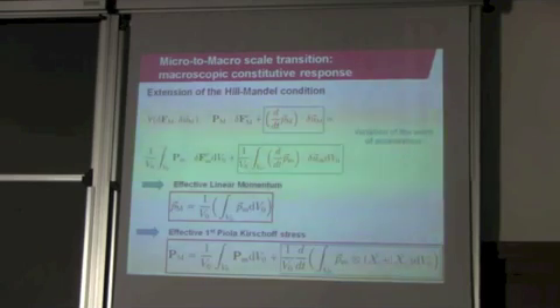And the effective Piola stress, so Francesco, it's Piola stress. By the way, just a side remark, it turns out that in homogenization at large strains, the Piola stress is a much handier measure than the Cauchy stress. So all homogenization at finite strains is usually written in Piola. Okay, but that was the side remark. So what's actually important here is that this is the scale transition for the stress.